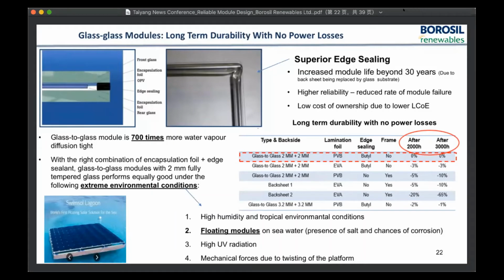A typical glass module is 700 times more water vapor diffusion tight as compared to the normal module. And with the right combination of encapsulation foil and edge sealing, the glass module with typically 2 mm fully tempered solar glass performs excellent and much better as compared to the normal module under the extreme environmental conditions. So these edge sealing ensures that the module lasts long even beyond 30 years.